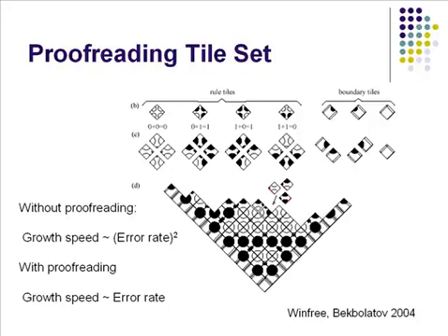By this implementation, you can reduce the rate of error, because when one tile has come here and it is mismatched, then the next tile does not stick to the place without making an additional error.